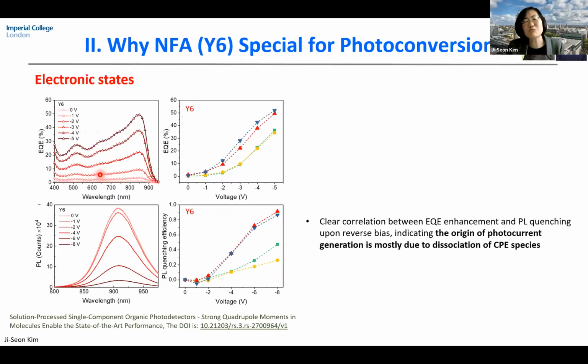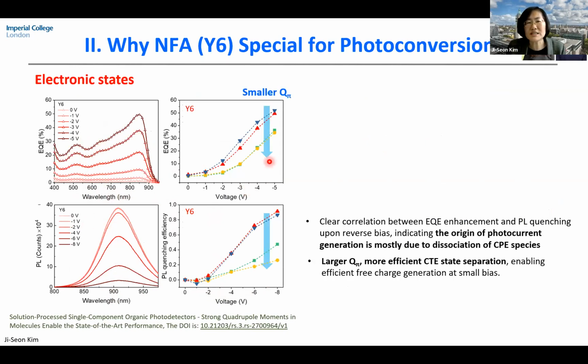So we have done a similar thing using this solution processable Y6. By quenching this emissive CT state by applying voltage, we can increase the external quantum efficiency of the device. Interestingly, when you change the NFA molecule to one with a different quadrupole magnitude, the quenching is reduced.